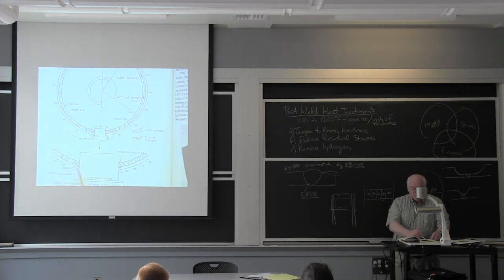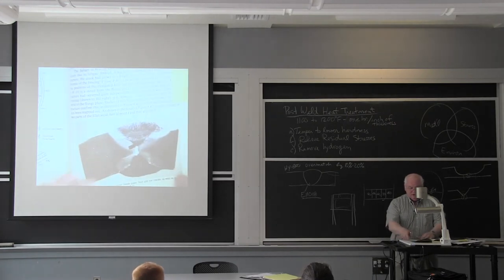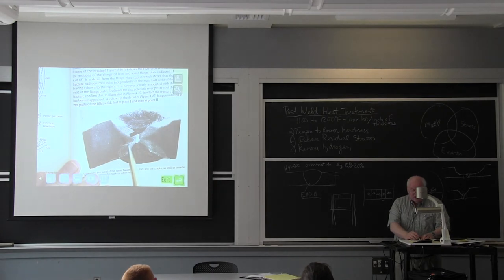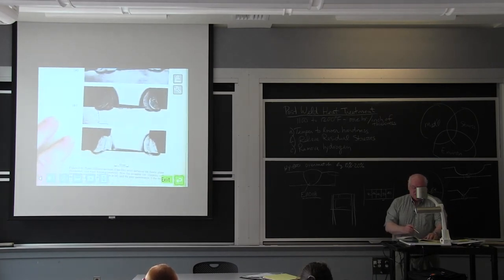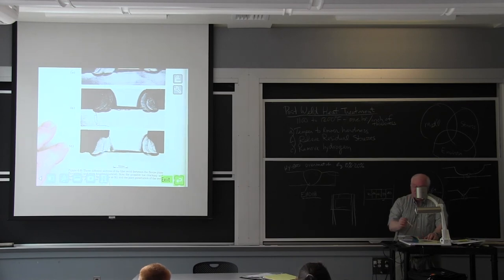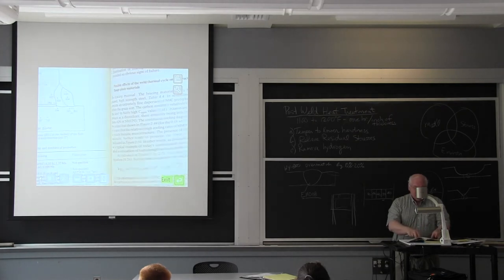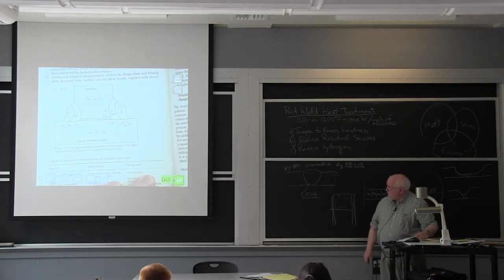They look at the thing afterwards and they see fatigue cracks starting from the fillet weld. And here, you can see they have a little bit of dye penetrant or something. You can see a lamellar tear here. You can see a little root crack down here on the weld. This is the actual weld they dug out of the ocean. Here are some other sections. You can see a nice crack right here in this thing. Here's the fatigue crack.